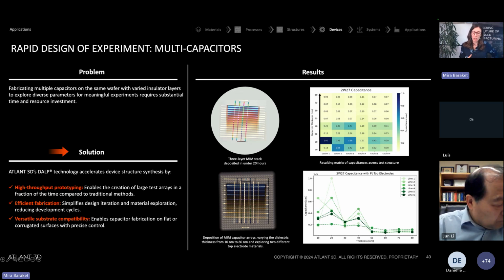So on the top, what we have changed is only the dielectric thickness, and on the bottom here, we've changed the dielectric thickness, but we have also used different deposition conditions for the top electrodes. So we are not only changing one parameter, but also multiple parameters, and this brings a lot of, I would say, faster iterations for innovation.